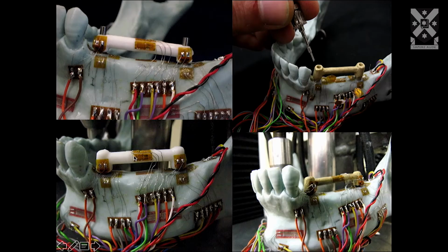So up here you see these little screws going in, and there you can see the screw holes. And down here there's no screw holes. That's what we call cement retained. So when you screw something together, you have a thing called compliance. There's a certain amount of movement and give in the combination of the screws. But when you cement retain, it's rigid. And depending on the flexing of the mandible when you're loading it, you can then rupture that cement attachment or that cement bond, and that becomes the weak link in the system.